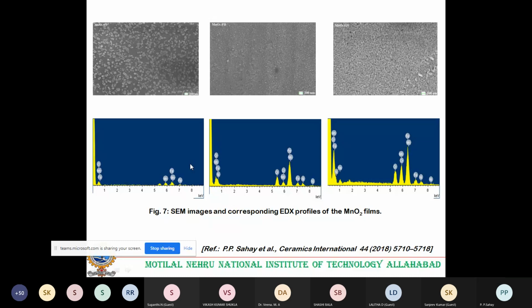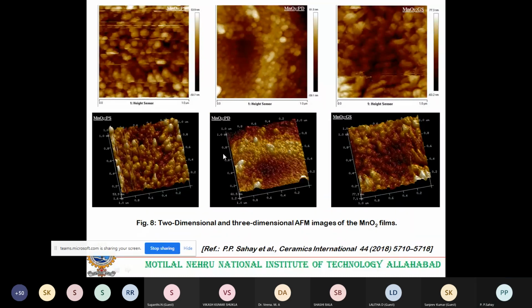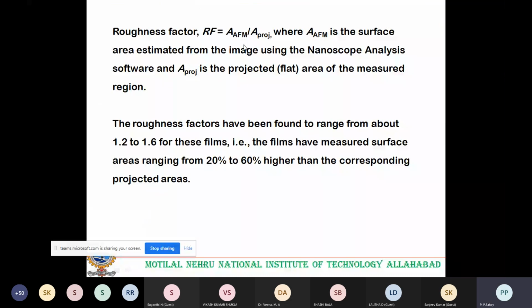Now you see, this is the AFM. This is 2-dimensional, 3-dimensional. In 3-dimensional, you see, we will calculate that we are using the terminology image surface area and image projected area, and here we have scanned the film around 1 micron into 1 micron. Okay, and this is the 2-dimensional. So with the image surface area and image projected area, we have calculated the roughness factor, that is A AFM. A AFM is the surface area estimated from the image, which you call the image surface area, and A projection, that is the image projected area.